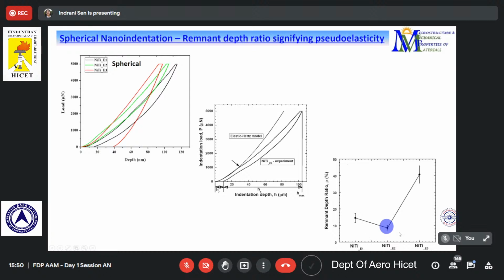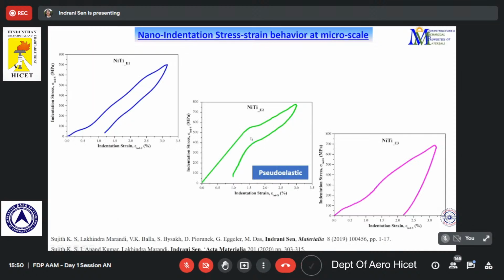So this one shows around 90% recoverability. You can see here with the green colored curve. This shows a very good amount of recoverability. And to check that, we have plotted the stress strain curve for these three alloys. Once again, the one E3 prepared with the highest energy density, because of the presence of martensite and precipitates, that restricts the recoverability, and there is a huge amount of plastic deformation.